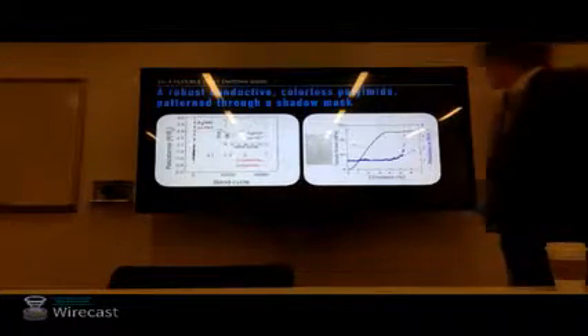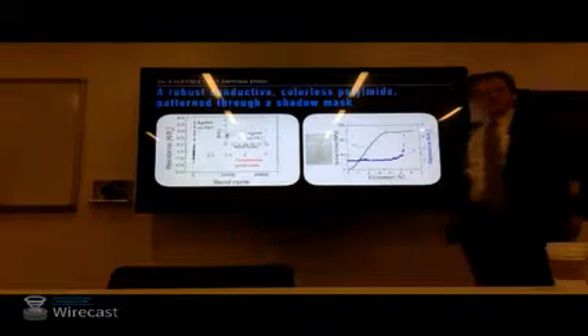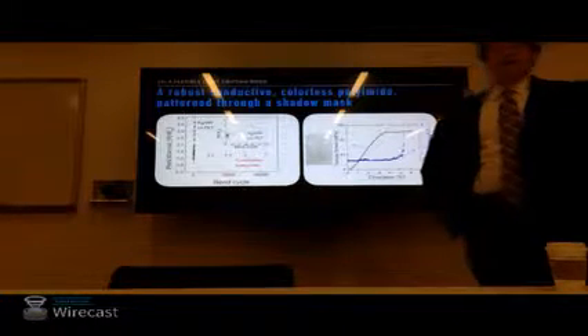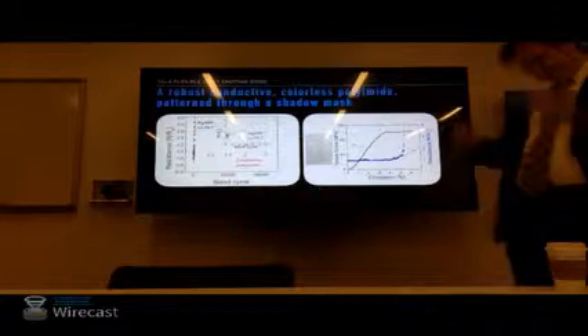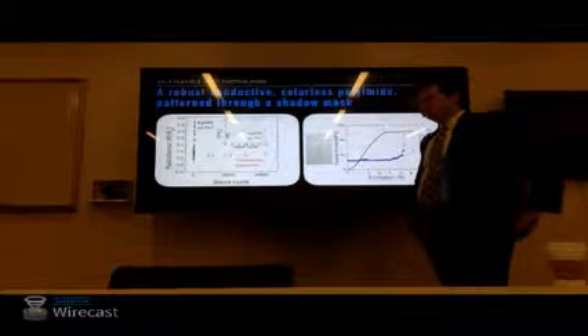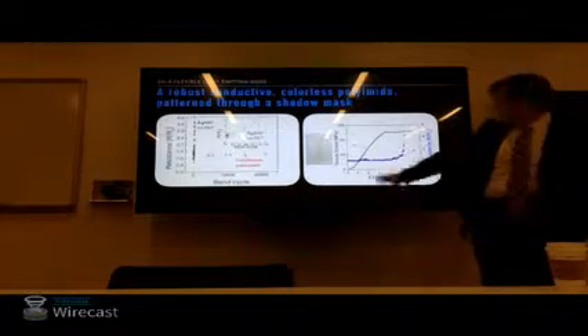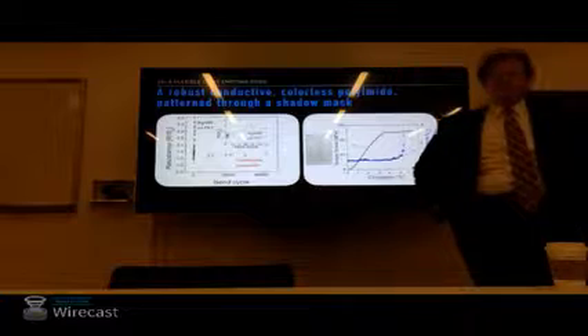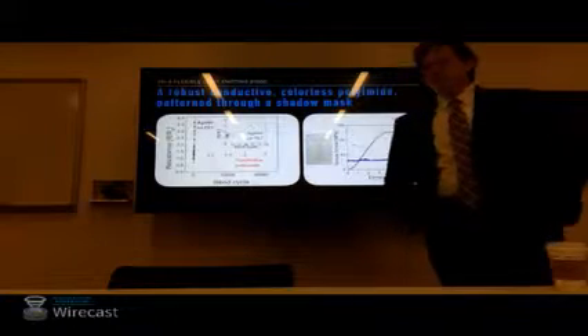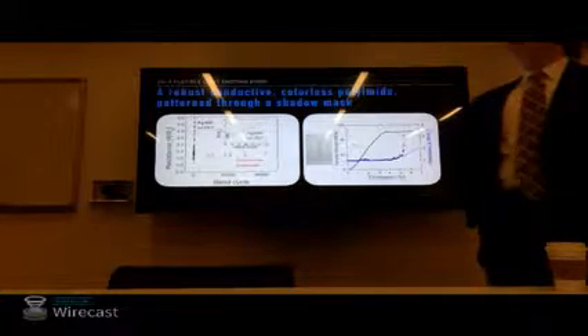We did a test with one of these. It's not reported here, it's in the thesis, where I took it up to, I think, 2.5% elongation for 50 cycles. Saw no change in conductivity. By that you mean you did 50 cycles, from 0 to some level and back to 0. And there was no hysteresis in your curve? In the curve, no. I mean, we're kind of low down. There's a bit here at the start, but I might blame that on the machine. Loading and unloading, right up in an elastic regime, to my accuracy of measure. Exactly.